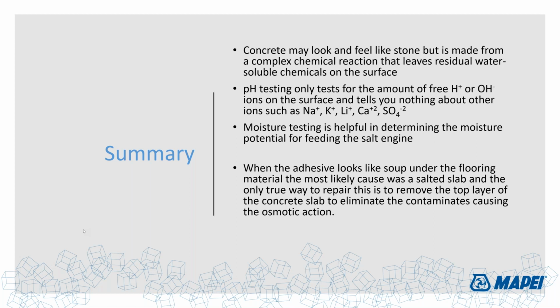So it's like doing an FTIR or some sort of chemical test that reads out a percentage of sodium ions on the surface. It doesn't really have anything to do with the water that's there, so that doesn't really impact it. What you're looking for is the residual ionic material on the surface, not necessarily the water. The water will actually get in the way of some of these test results. You want it gone anyway.